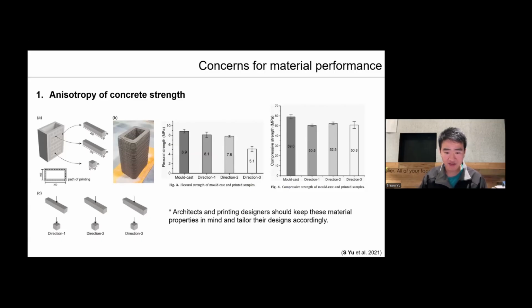When we test flexural strength in this direction, the sample tends to fail by tearing along the interlayer bonding. As a result, the flexural strength and tensile strength here is significantly lower than others. This highlights the importance for architects and structural engineers in the design. So they need to be aware of this material behavior and tailor their design accordingly.